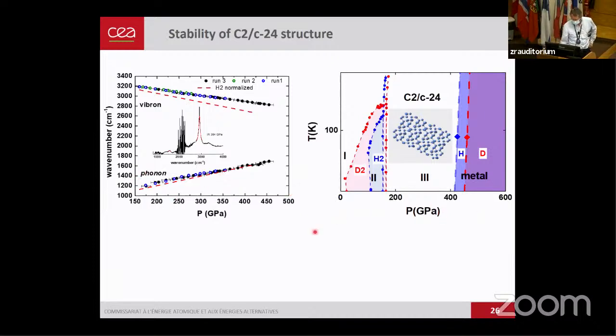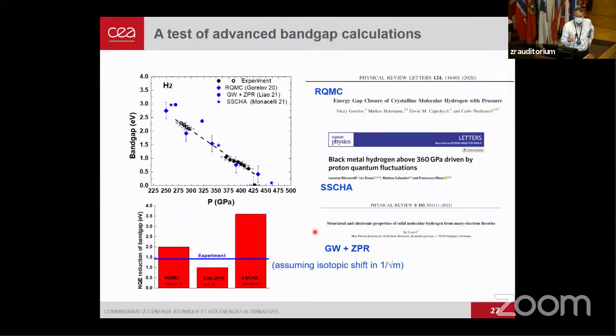And then, since we published our measurements on hydrogen, there have been many ab initio calculations trying to calculate the gap of this C2/c phase. To calculate the gap, you have to go to more advanced calculations. There was one doing quantum Monte Carlo calculations, where you treat protons and electrons at the same level, and their gap matches quite well with our evolution of the gap. Then there was another calculation doing path integral molecular dynamics simulations, and again, these stars match well.